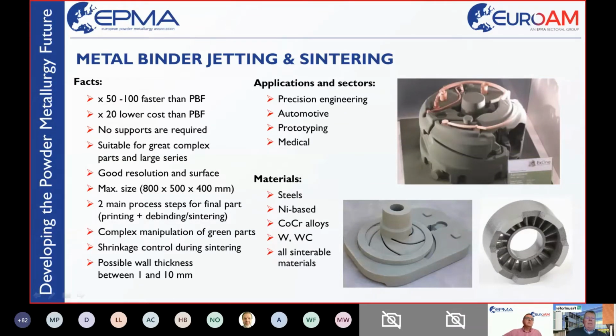That's at least assumed. Of course, you need two process steps, printing plus debinding and sintering, but for the powder bed fusion processes, mostly also thermal treatment is necessary after the printing step. You have green parts to be handled in the end.